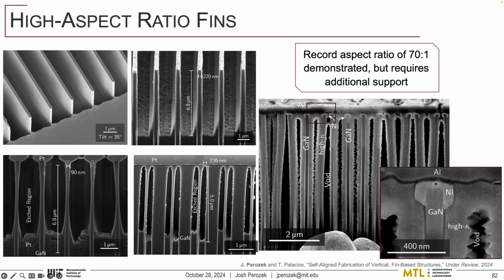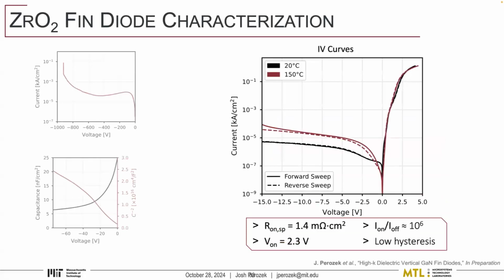And they're so narrow that the gallium nitride actually starts bending. If we were to go any further than that, you can see this image on the right. These fins are just leaning into each other. So we're kind of pushing against the limits that you can do with GaN without having some form of extra support within it. To go into the performance of these diodes, they behave as you would expect for a Schottky